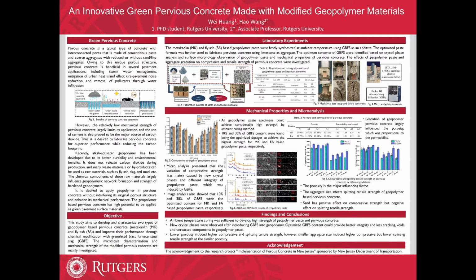We can find the metakaolin-based geopolymer paste with 10% of GBFS has the lowest defects area, which is 3.6%. And also we can find the fly ash-based geopolymer paste with 30% of the GBFS has the smallest defects area. This result is in accordance with the compressive result.